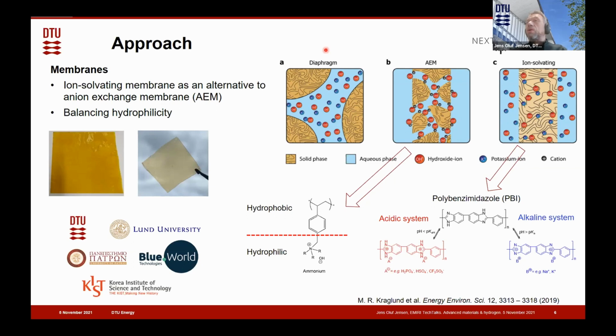But in many groups, the dream is to develop an anion exchange membrane with side chains that resembles that used in the PEM electrolyzer, just with cations immobilized on the side chains instead of anions. And they are typically, instead of sulfonic acid, a quaternary ammonium ion. These membranes, they behave very well these days. They have, in very recent years, obtained conductivity that is really high enough for excellent performance, but the stability is still an issue. And the big problem here is very often that the side chains are the weak part, so they break down fast. So our idea is to say we're going to do without these side chains.